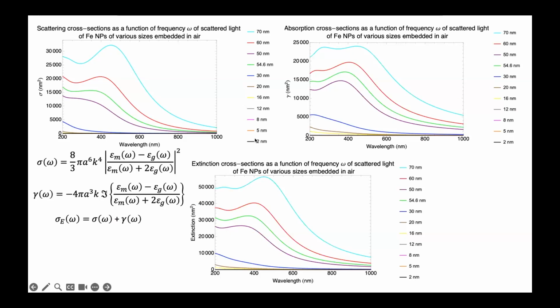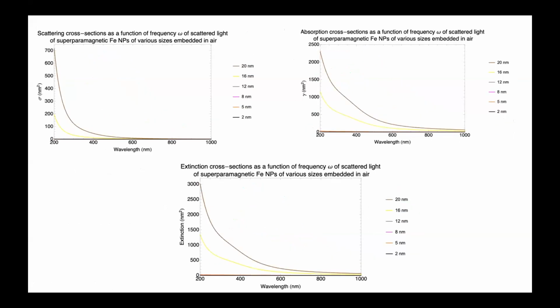Looking at my calculations, we look at nanoparticles from 2 nanometers to 70 nanometers. As you can see here, we see some scattering starting to dominate at around 30 nanometers. So now I know that when I go to the lab, I should try to produce nanoparticles of about 2 to 20 nanometers. These nanoparticles are usually referred to as superparamagnetic nanoparticles, as the particles behave as if they have a net magnetic moment, but do not possess a permanent magnetic dipole.